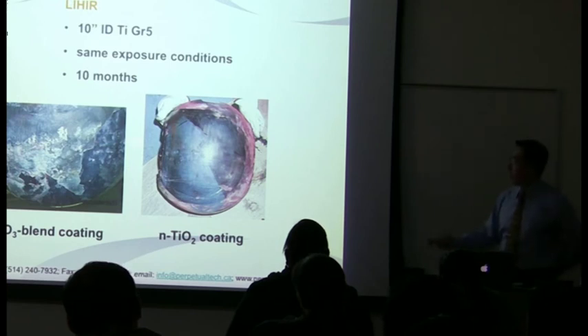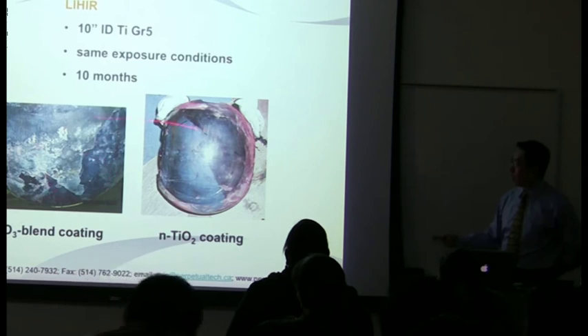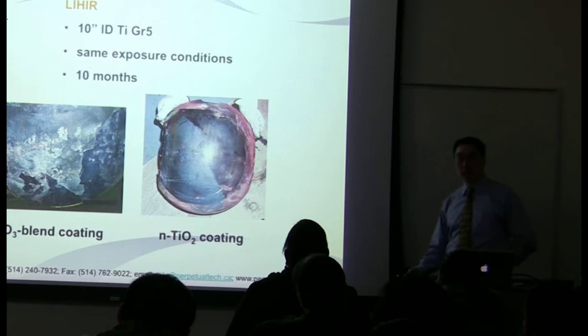So after 10 months, they had leakage in this valve, so they removed both to look at it. You can see there's gross spallation of the coating on the chromium sample, whereas with the nano-TiO2, these red regions are scale built up. But the coating remained intact, and I believe they put it back into service for more use.